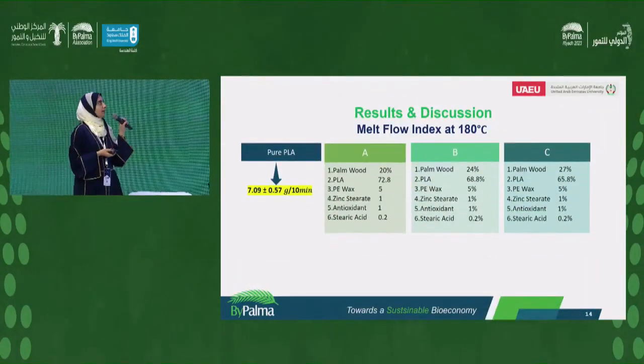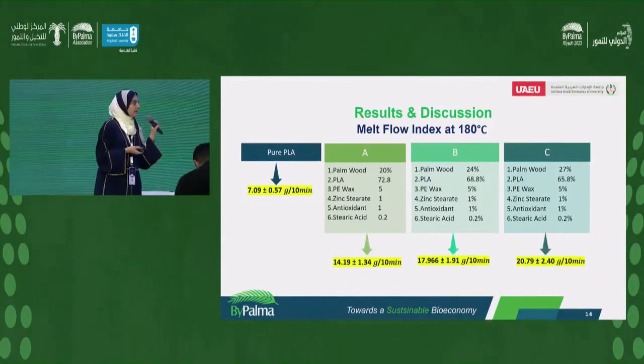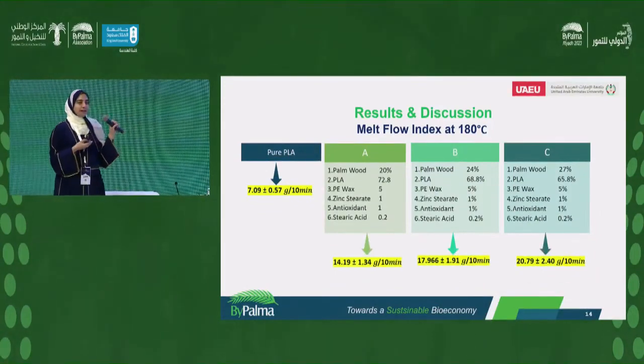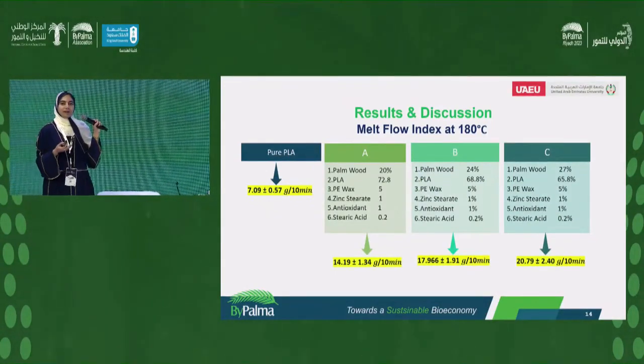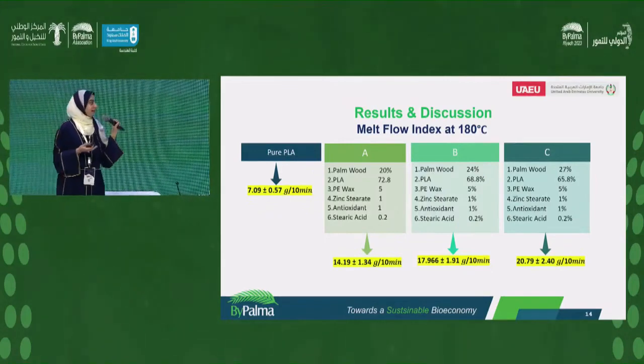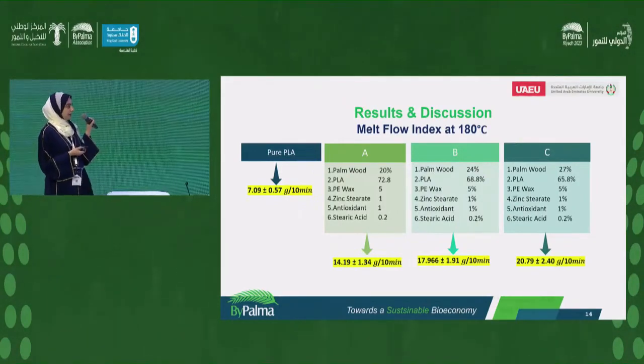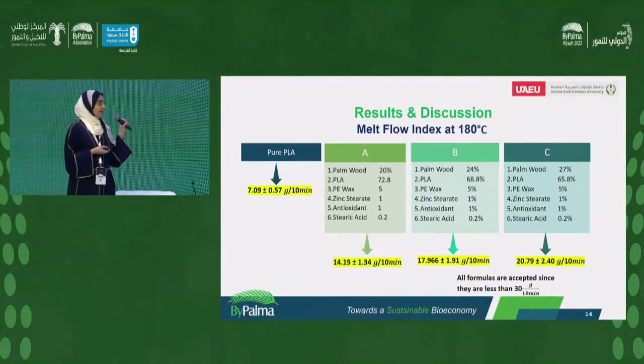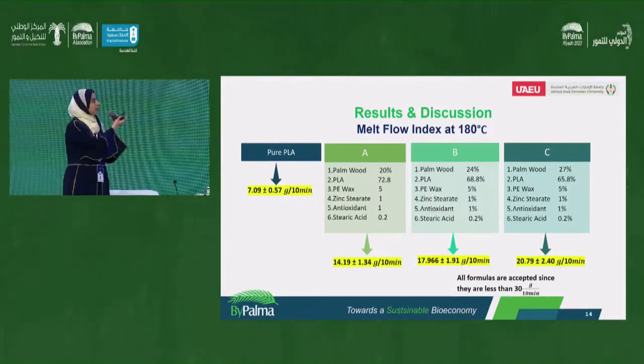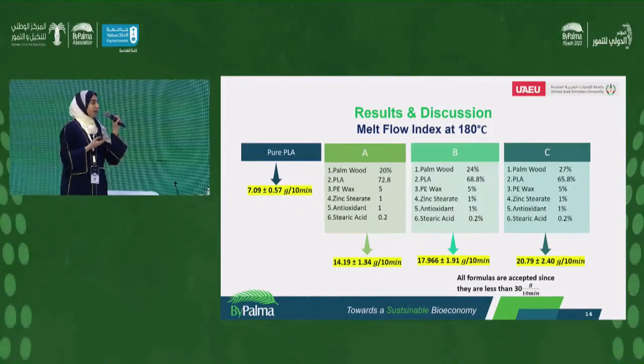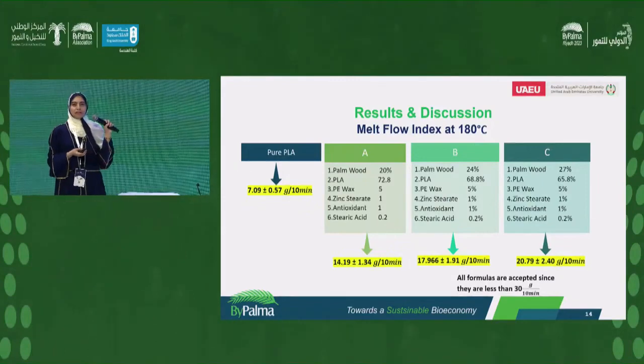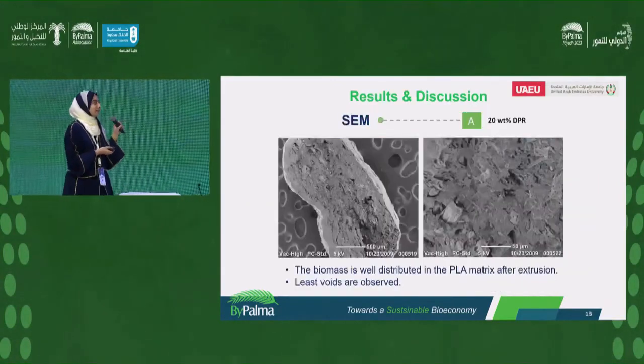We also did melt flow index to ensure that the flowability of our product can fit the machinery available in the factories, and the flowability will be accepted. So all the three optimized formulas are below 30 grams per 10 minutes, so it is acceptable.